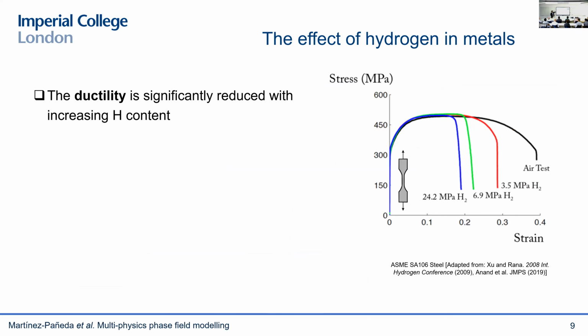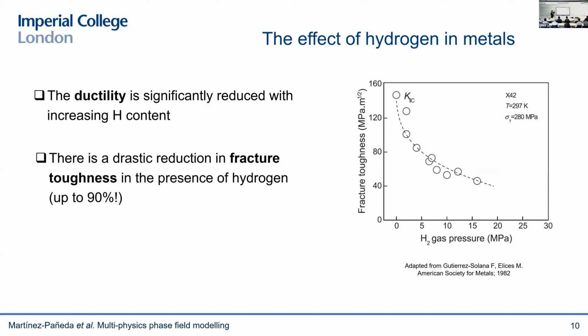So one of the things that we see, for example, is a very significant reduction in ductility. So here we have metallic samples, dog-bone samples, uniaxial tension test. And you can see that if I expose my metallic samples to hydrogen, for example, by exposing them to hydrogen gas, then I get a very significant reduction in failure strain. Another thing that we see is a very drastic reduction in fracture toughness. So this is fracture toughness versus hydrogen content. And you can see that we go from 150 megapascals root meter to well below 40 megapascals root meter with increasing amount of hydrogen. And this is for a low strength steel. But in high strength steels, the reduction in fracture resistance can be of up to 90%.